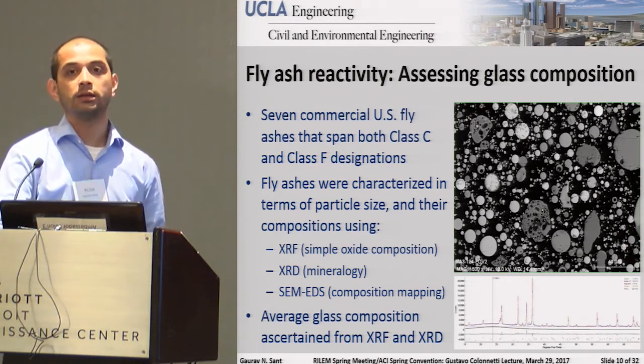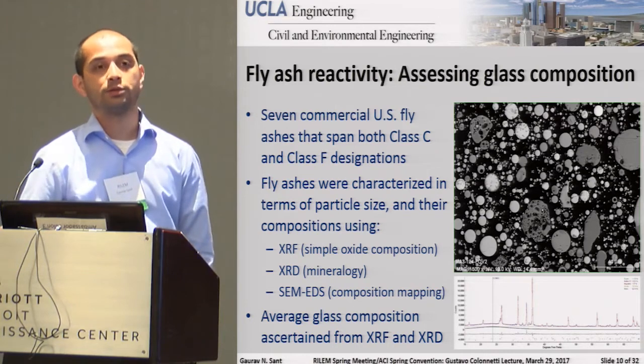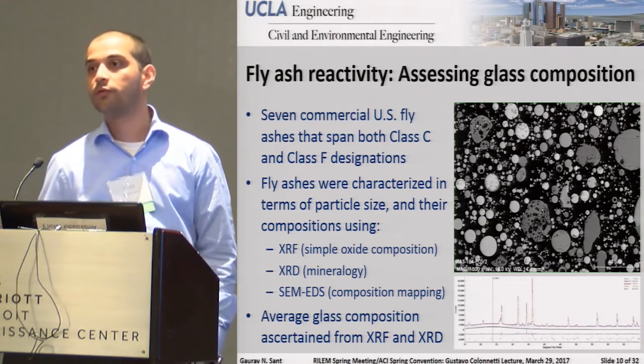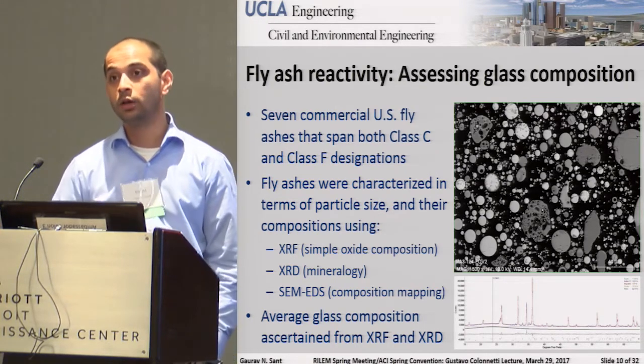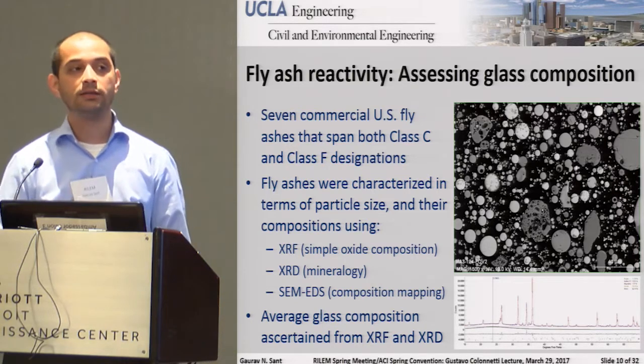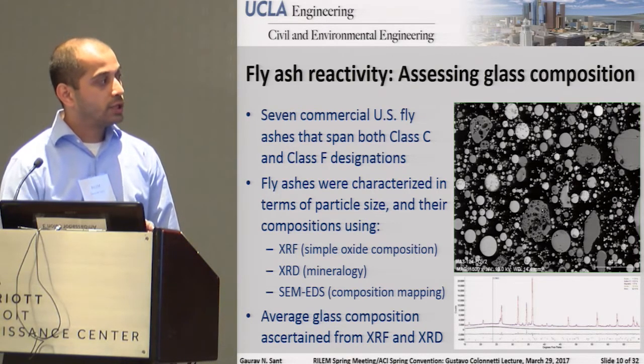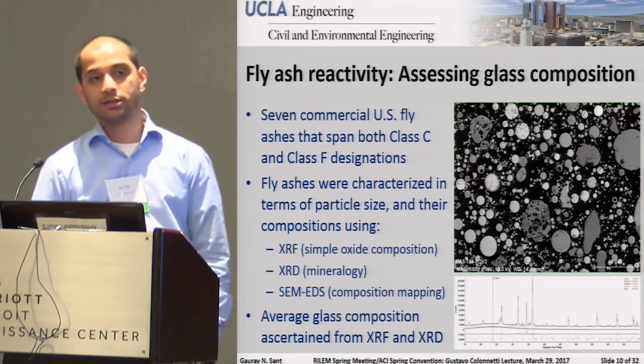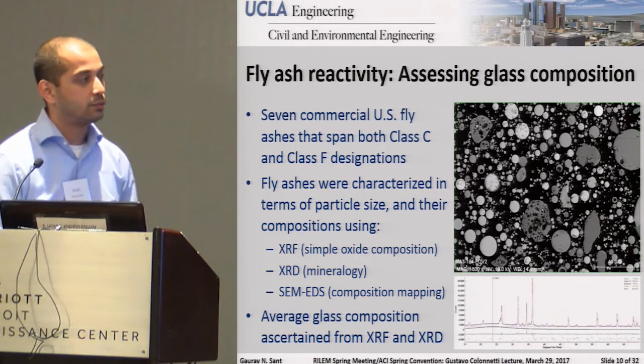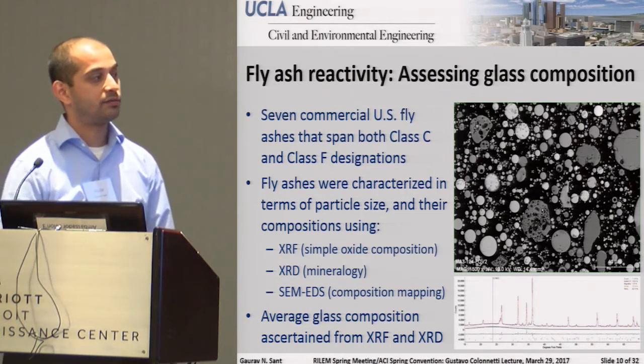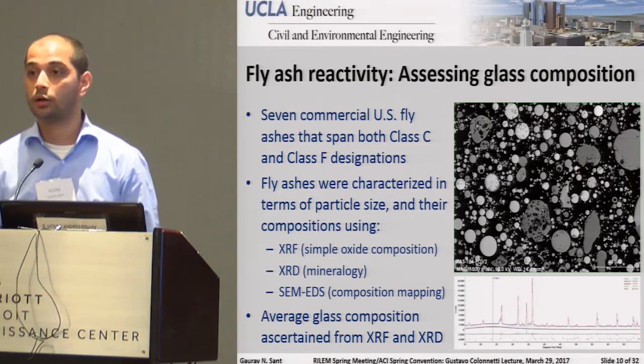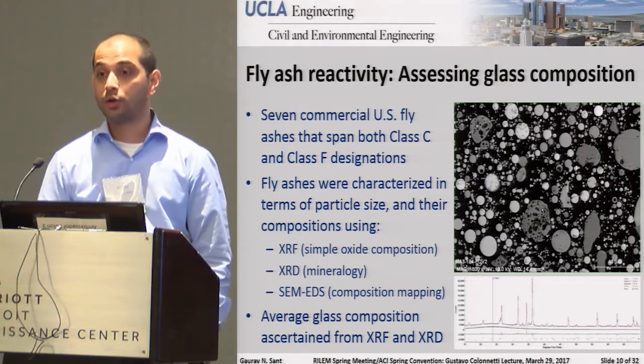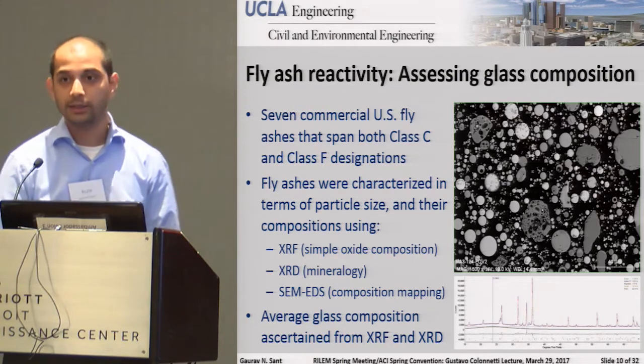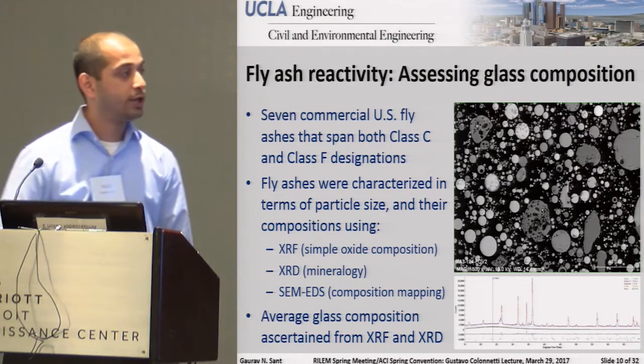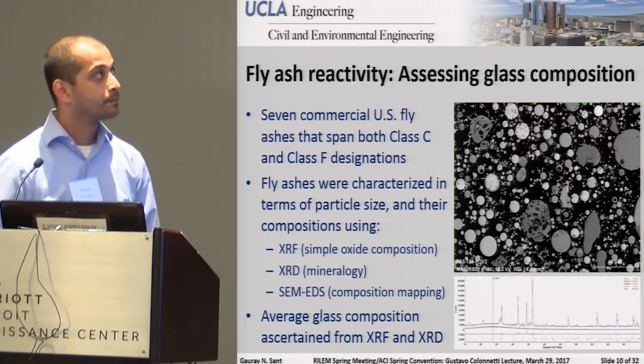We, of course, do understand that there's a lot of heterogeneity in the composition of the glass in a fly ash. However, that heterogeneity is not really very useful, because while you can map it, what it means is really not clear. So we wanted to see what we can really determine from the average glass composition. The nice thing about doing the subtractive method of trying to take the XRF data and remove all the crystalline compounds from it is you're left with the average composition. So it's quite a straightforward process. You basically just do a mass balance calculation, which yields the composition of the glass.